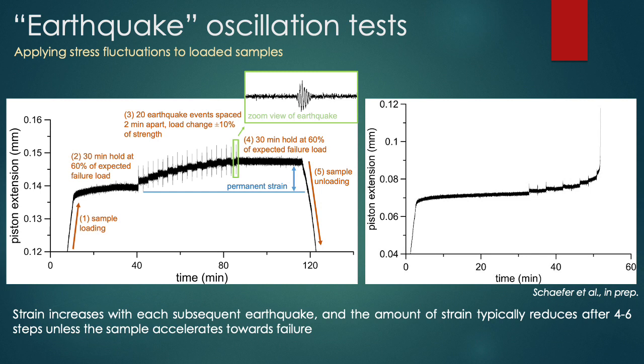We scaled the events to the material strength, oscillating by plus and minus 10% of the material strength, whilst monitoring the strain response. If the materials survived these oscillations, we then returned to another 30-minute load-hold phase to observe whether the material behaved differently, and the difference in the absolute strain between the first and the second load-hold we interpret to be permanent strain resulting from the oscillations. In the case of sample failure, the degrading impact of the oscillations was clear already. Here you can see two examples.